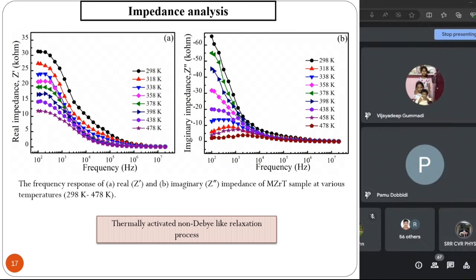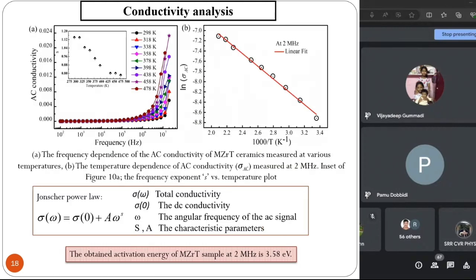When you look at the microstructure of the material, you have seen nice grains possible. We want to figure out what is the contribution from the grain and the grain boundary. If you have more grain boundary, then your material will be very lossy. But if you have very good grains, you will have the best material response. So in order to find that out, we have done this, and we see that the loss increases at higher frequency because of higher temperature, because there is a conduction that is getting increased in this case of material. Can you go to the next slide, please?